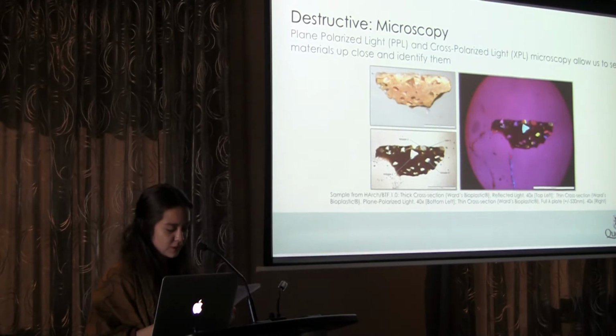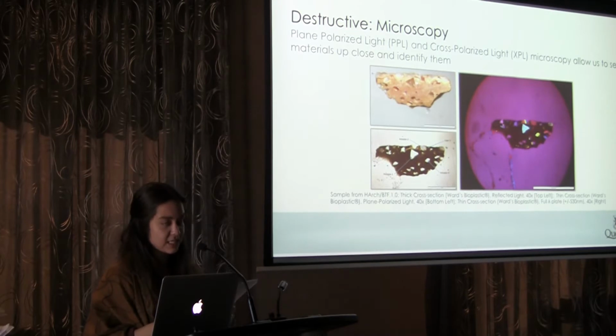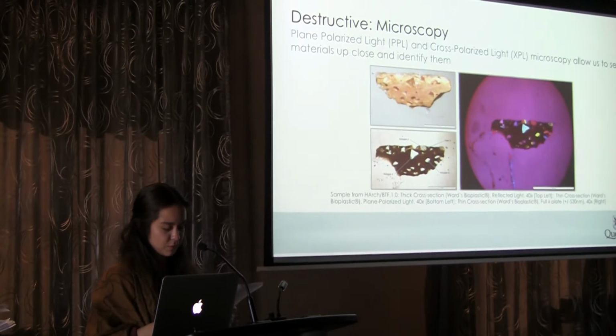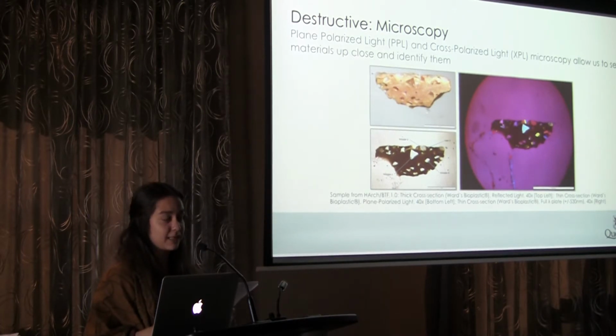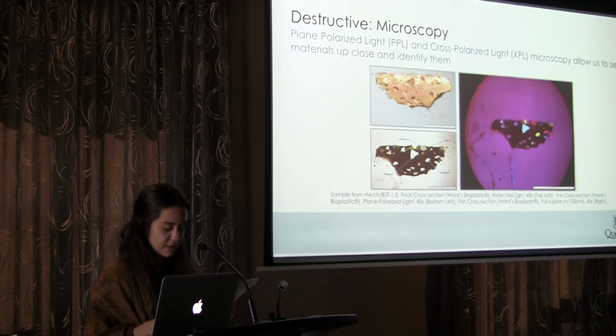Since tempered particles are often polymineralic in nature, this may confirm the inclusions' addition as part of the temper recipe. Furthermore, since tempered particles are often angular rather than rounded from erosion and weathering processes experienced by clay itself, this may also confirm that the inclusions were added intentionally as part of the temper to the clay mixture.